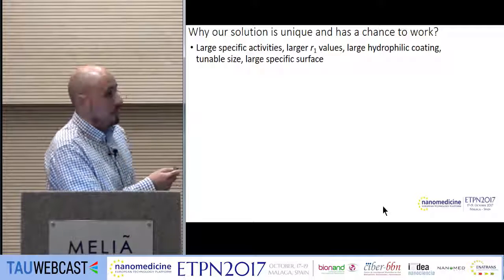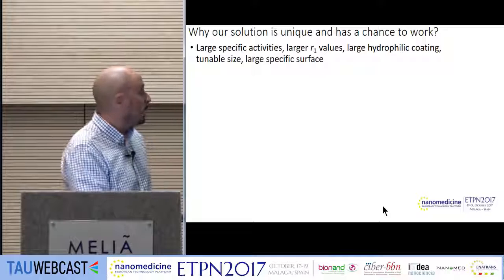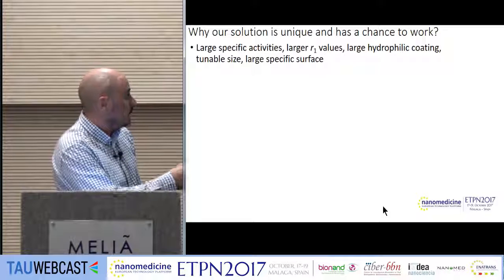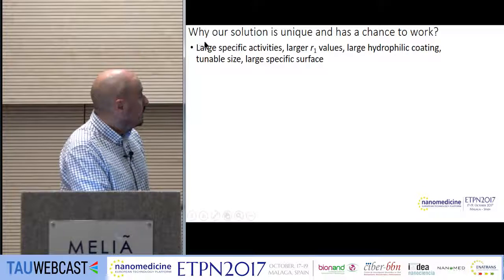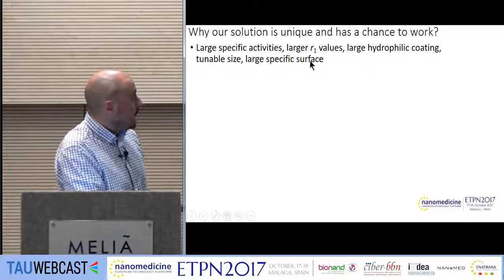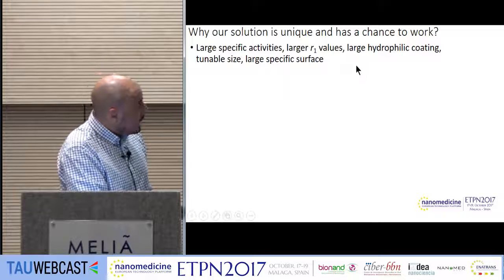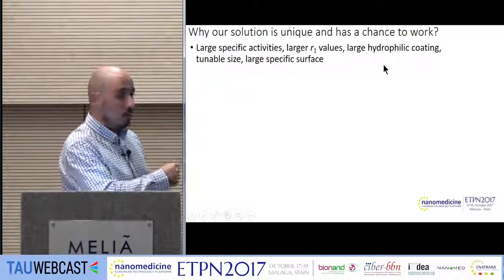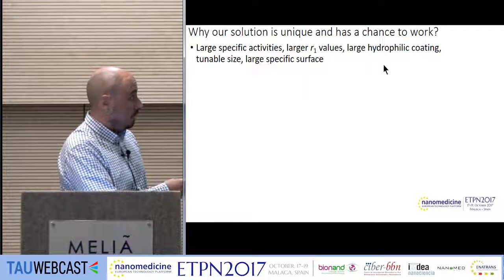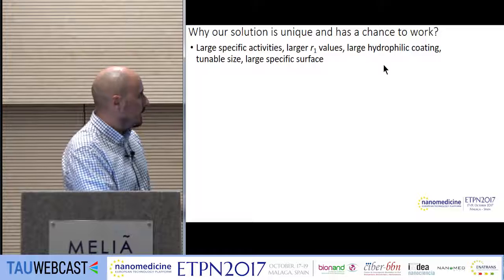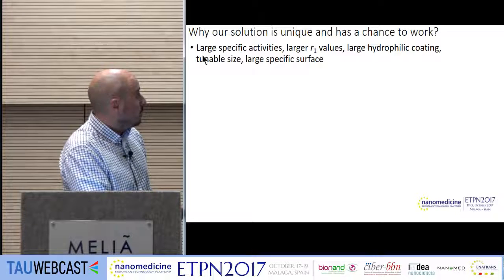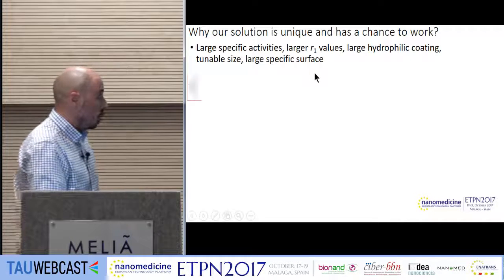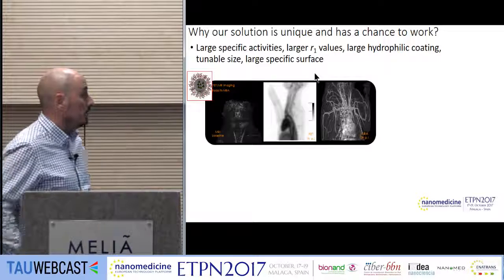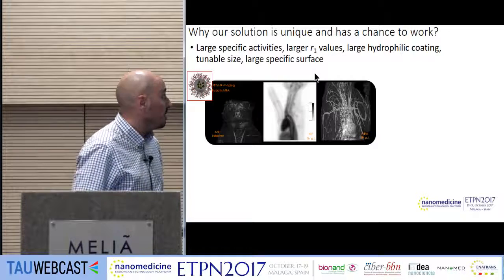I think because of the type of technology we have developed, because of the features it presents. Just to mention some of them, they show a large specific activity, very large R1 value, and a large hydrophilic coating that helps you functionalize them even with very, very hydrophobic peptides, as I will show you now. They are tunable in size, so you can have different properties, and they have a very large specific surface. We have been applying this in the last couple of years for different applications.